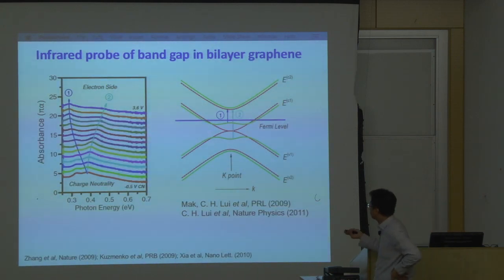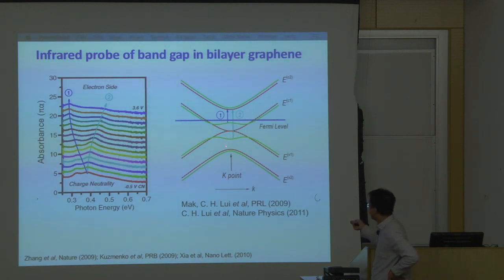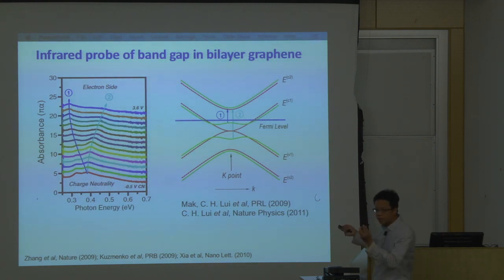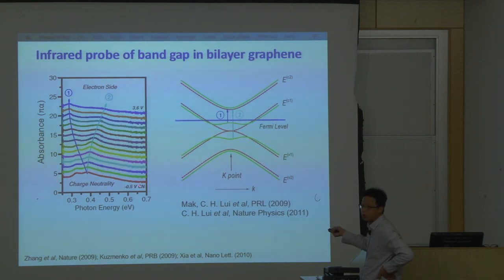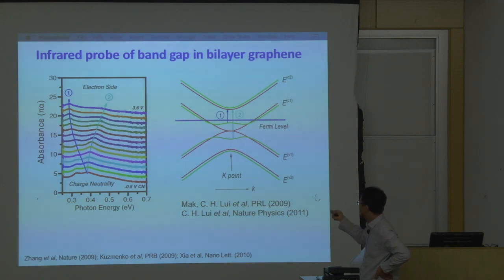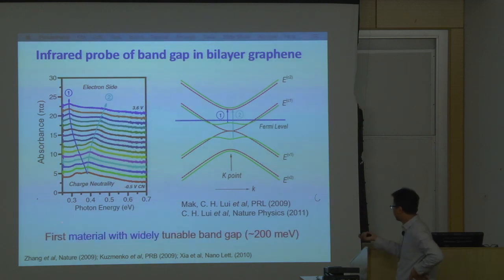This is the result I got when I was a student about seven or eight years ago studying bilayer graphene. The red curve is the band structure of bilayer graphene in pristine form. If you apply an electric field by injecting electrons, the Fermi level raises and the internal electric field from the gating opens the band gap. The initial interband transition here separates into two transitions, A and B. We measure the electronic transition using infrared absorption spectroscopy, and we see the transition peak split into two separated peaks. The separation of these two peaks corresponds to the gap size — tunable from zero to about 200 meV.